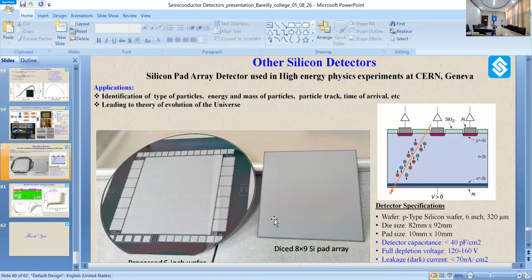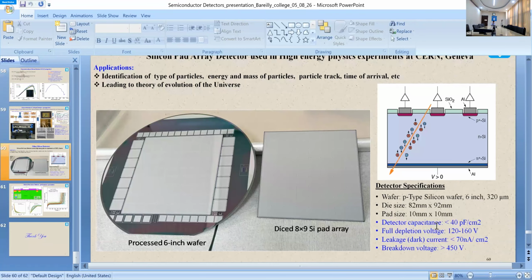This is what we call the 8x9 silicon pad detector. It uses a very high resistive wafer so that it has a very high breakdown voltage. You can see from the detector specifications that the breakdown voltage generally needs to be greater than 500 volt or 450 volt, so a very high resistive wafer is required. The operating voltage is 120 to 160 volt, so we also need a specific resistivity and specific thickness of the detectors. The thickness is also important to estimate the energy of the incoming charged particles falling on the detectors.